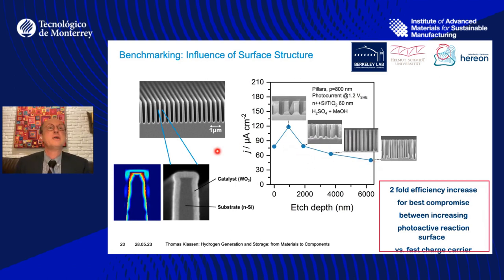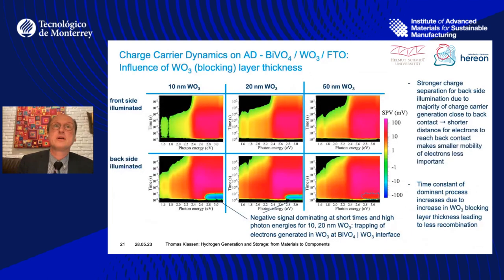This is the reason. And if you do the simulation, you recognize that a lot of light is already absorbed at the tips here, and there's not much light penetrating into the depth of these structures. So this is why we can say with a certain roughness, you get better results. But the good results that we have cannot be all due to the surface roughness.